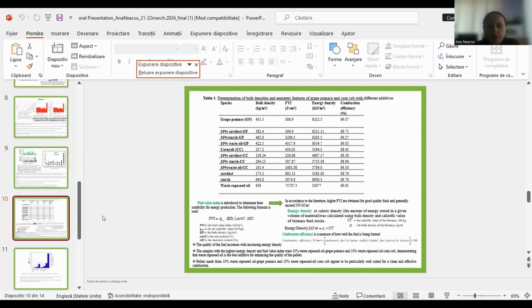The quality of the fuel increases when energy density increases. The samples with the highest energy density and fuel value index were 10% waste rapeseed oil with grape pomace, and 10% waste rapeseed oil with corn cob, demonstrating that the waste rapeseed oil is the best additive for enhancing the quality of the pellets.